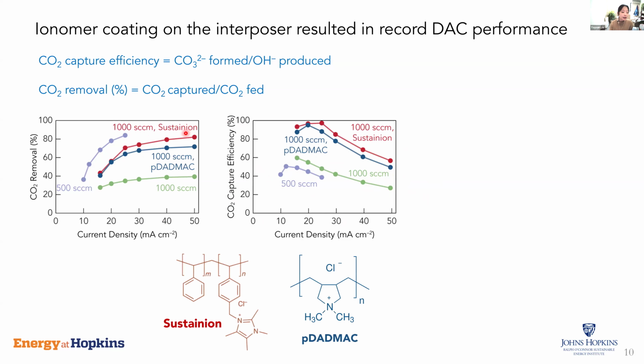What we discovered is that on top of the resin bead, we can also introduce a thin layer of coating of anionic conductive ionomer. So we tried two different kind of ionomers. One is called Sustainion, which is a commercially available ionomer, and the other one is a synthetic ionomer from our lab, which is called pDADMAC.